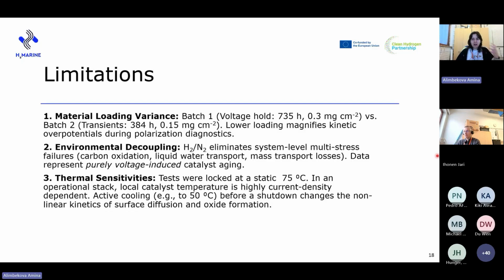While this variance limits the qualitative alignment of our values, the normalized degradation trends are quite consistent, including when comparing the crystallite growth with the postmortem analysis. Our intentional choice of hydrogen-nitrogen atmosphere during the accelerated stress tests frames the whole study as specifically voltage-driven catalyst degradation mechanisms.